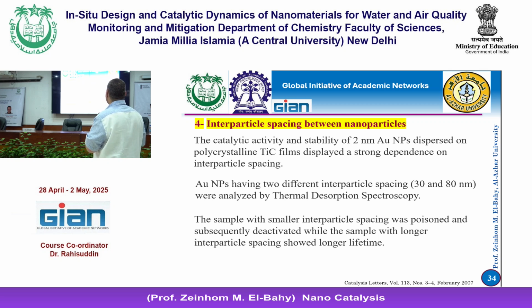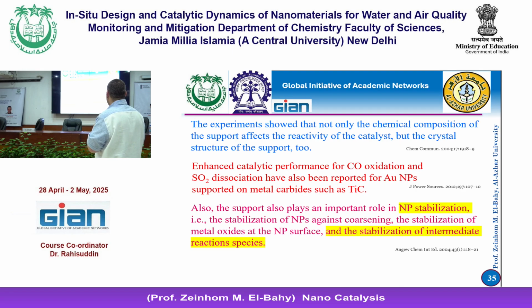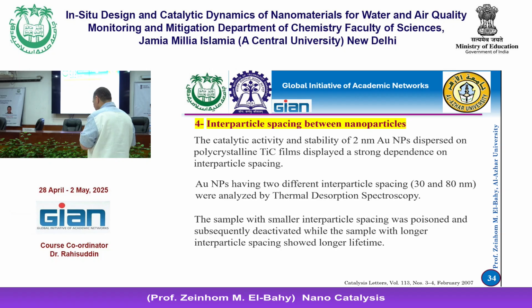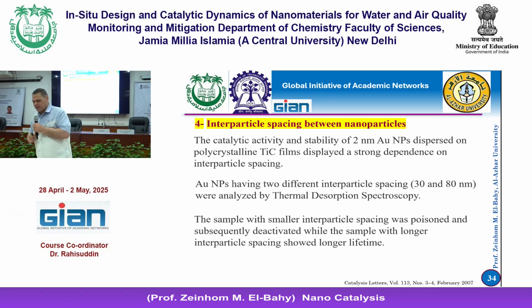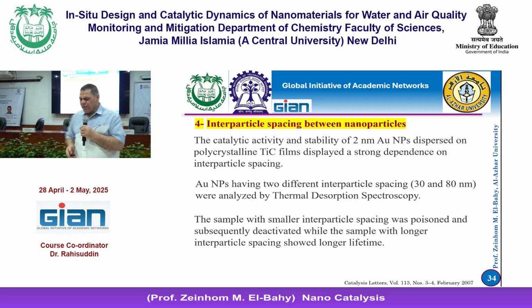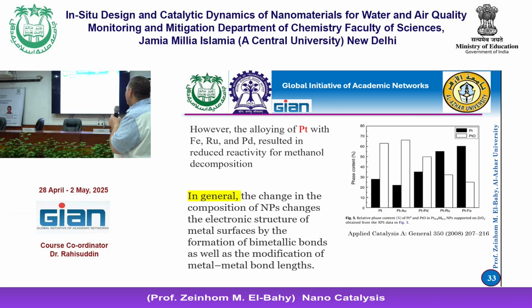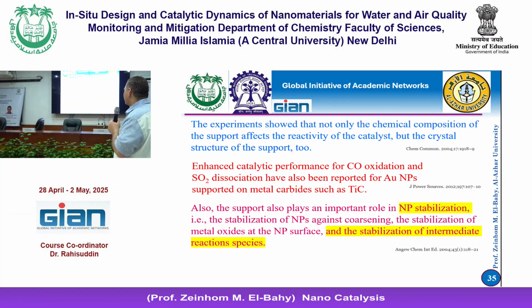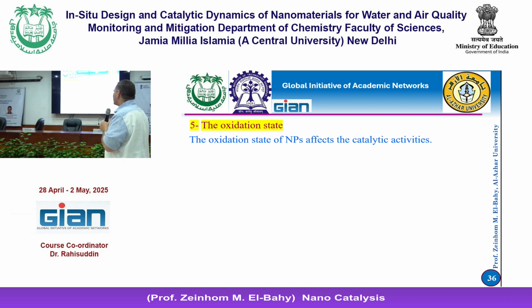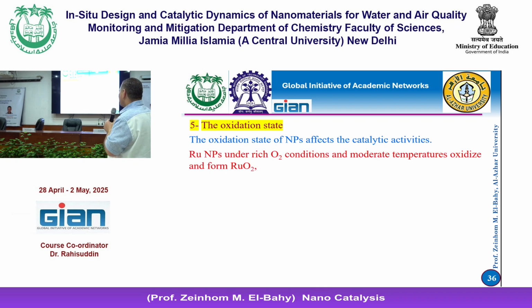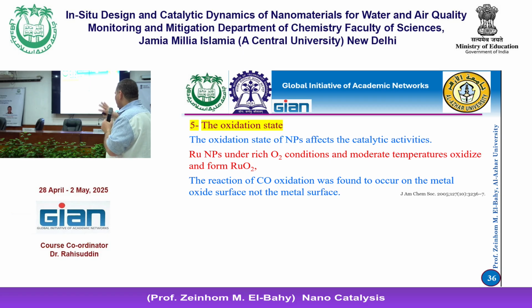The fourth effect is the interparticle spacing between nanoparticles. We just mentioned that the change in interparticle spacing will change the catalytic activity of the particles, like the catalytic activity and stability of 2 nanometer gold dispersed on polycrystalline titanium carbide films, which displayed a strong dependence on the interparticle spacing. Because when it was 30 nanometer and 80 nanometer, it gave different catalytic activity. I think I have also just mentioned this data about it.